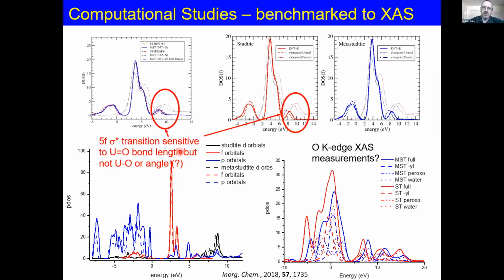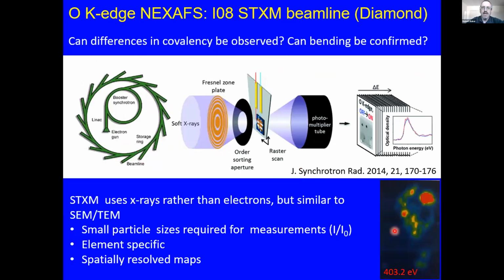So what about the oxygen side? These are the density of states plots for studtite and metastudtite on the oxygen edges. And you can see that from the theory, at least, there are some shifts that we may be able to resolve using oxygen K-edge measurements.